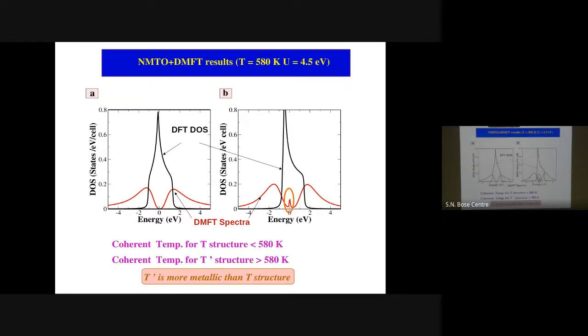And in this T and T prime structure, if you do a dynamical mean field theory calculation, this is the DFT DOS of T and T prime. You have just one band, so the density of states is pretty simple. But you can already find that this density of states for the T structure is kind of symmetric around zero. There's a particle-hole symmetry. In the case of the T prime, this is highly asymmetric. But if you do the DMFT calculation, shown with this red spectrum, the T structure develops a quasi-particle peak, while the T prime has a kind of a gap. Of course, both were metals at the DFT level, but if you take into account the effect of this strong correlation, in one case it gives rise to this quasi-particle peak and nothing in the other case.